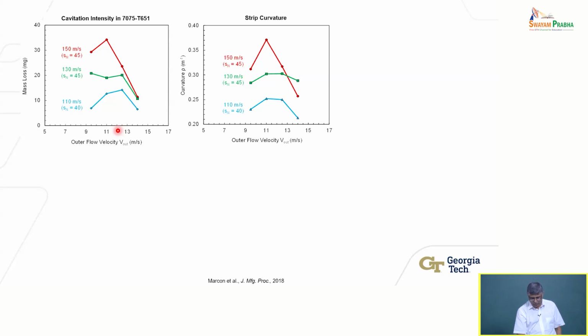So here it shows you for those same conditions what the strip curvature is. The curvature itself is greatest for that 150 meters per second inner jet velocity and 11 meters per second, suggesting that under those conditions I generate the highest amount of residual stress with our system. If you have a much more powerful system, maybe you can do more, but it gives me an understanding of how these two knobs of velocity affect residual stress generation, right?